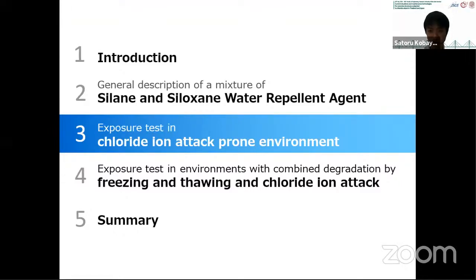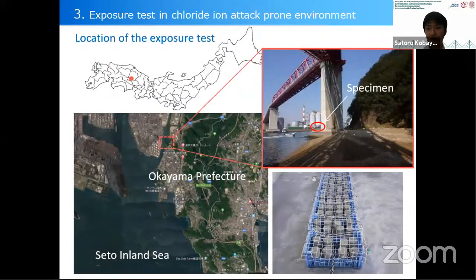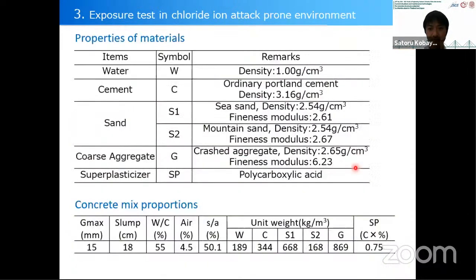First of all, we exposed the specimens to a chloride attack environment. The site for the exposure test is the coast of Okayama Prefecture in Japan. So here is Okayama Prefecture. And the specimens were set up like in the photo, on the footing of the bridge pier near the sea. So this is a satellite view of the sea. This is the point of the exposure test, very near the sea. We prepared a plastic box and cover net, and we protected the specimens on top of the footing. This area is a splash zone, so sometimes the specimens will be wet and sometimes they will dry.